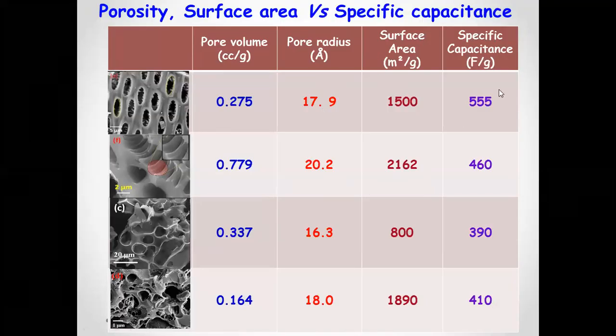So here, to summarize and show you the performance of the different activated carbons, we have put various parameters. These are 4 different carbons derived from different sources. This is the pore volume, this is the pore radius, this is the surface area, this is the performance. Here you see, the surface area is very high for this carbon, but the performance is very poor. I cannot say it's poor, but it's very low when compared to this. Even this 800 meters squared per gram carbon shows reasonably good performance.